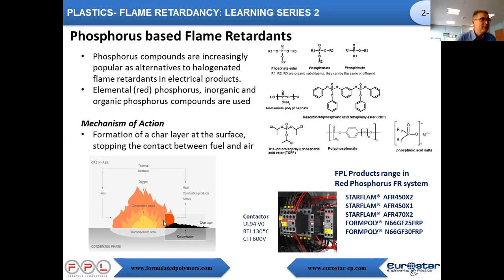They work typically in the carbonization, in the condensed phase. How do they work? They are called intumescent systems, meaning while burning, they create a strong char on the surface of the polymer and insulate the polymer from the air or the oxygen. So this char prevents the fire from propagating. These are not very simple systems. Most of the time they are binary or ternary systems of flame retardants. The most famous one is a combination of melamine polyphosphate with a metal phosphinate, in some cases aluminium or zinc phosphinate, and a synergist that can be, for example, zinc borate.